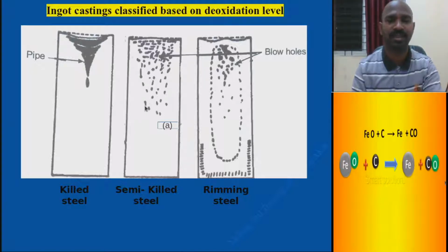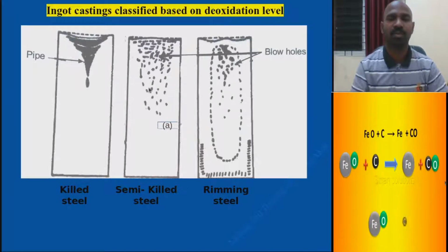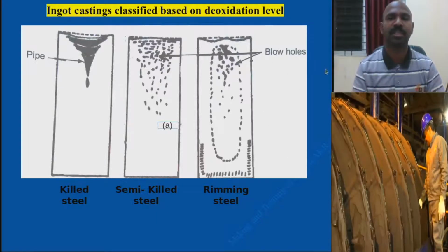They are taken to the surface, and you can compensate by stripping off less surface. Similarly in rimming steel also, but for killed steel you need to strip off a large amount of steel. Even these pipes also get welded at the hot rolling stage in the subsequent operations after ingot casting, at the finishing operation steps.